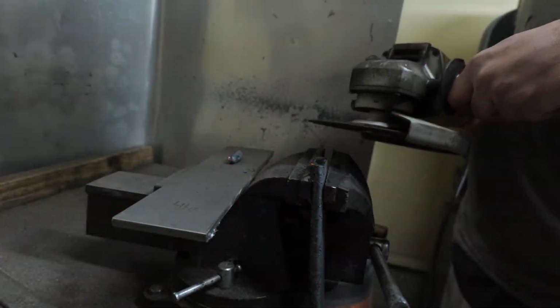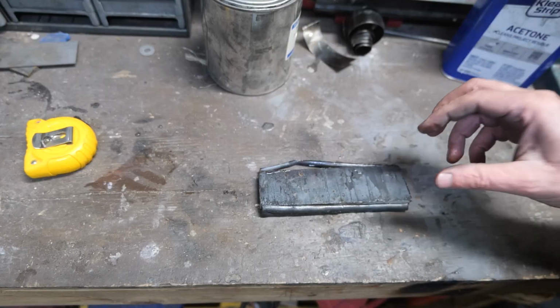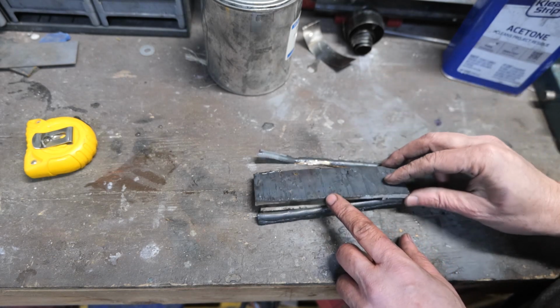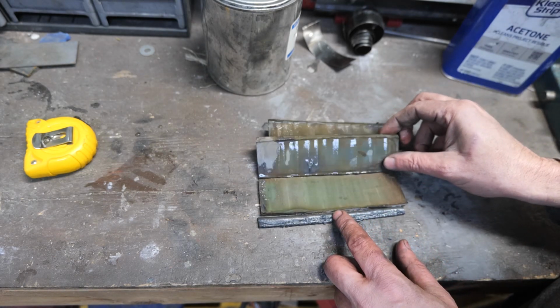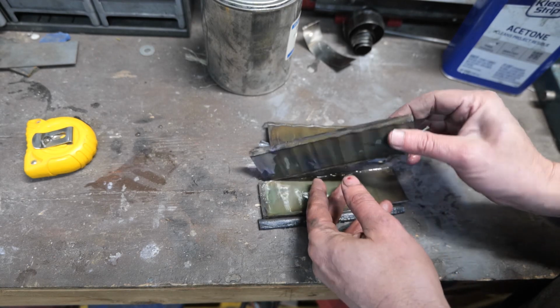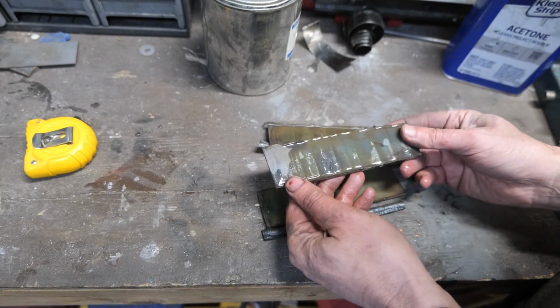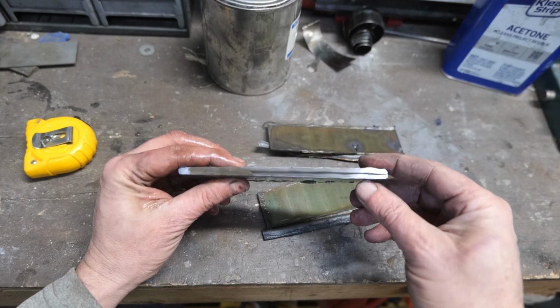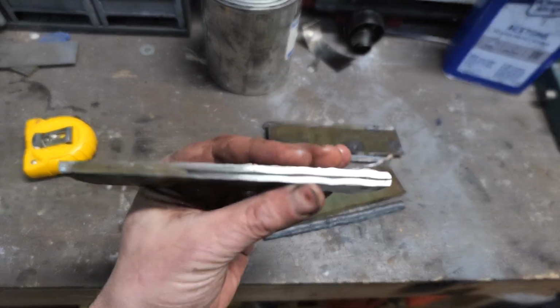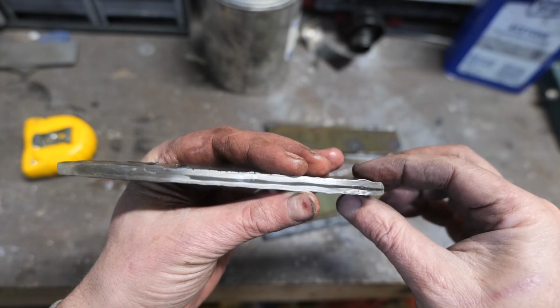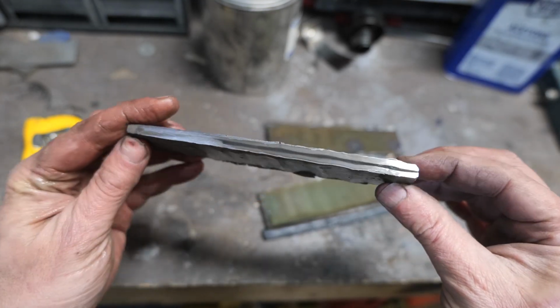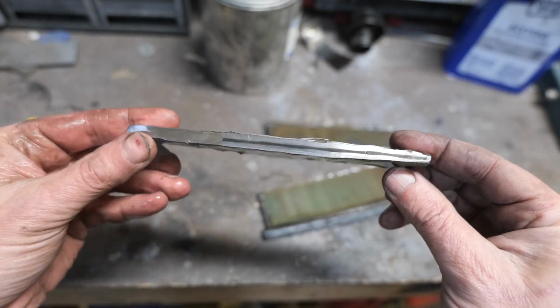Because the canister is stainless, it doesn't really forge weld to the jacket, which is also stainless, so it's easy to cut out of here. I do have to grind some iron off the sides, but after that, I've etched it to check the center line, and the core looks pretty good. Well centered. There's no reason it shouldn't be, but it's good to check it out.